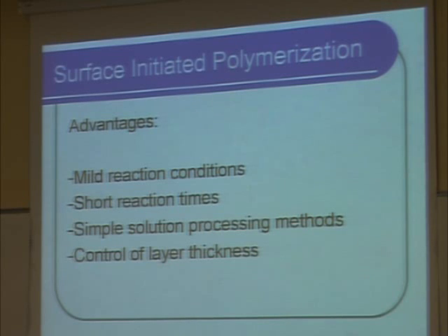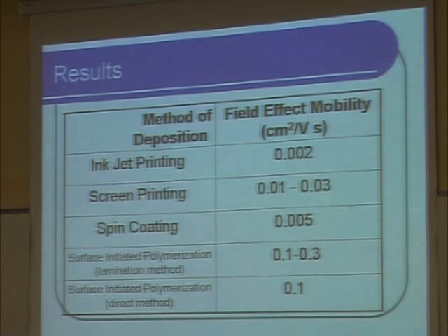The main advantage of using surface-initiated polymerization compared to the others is that it allows the formation of densely packed polymers over any surface topology. Other advantages include mild reaction conditions, short reaction times, simple solution processing methods, and the control of layer thickness by controlling the polymerization conditions.